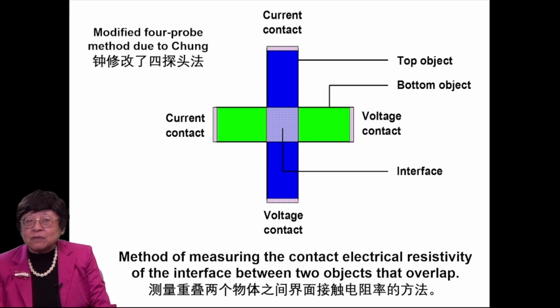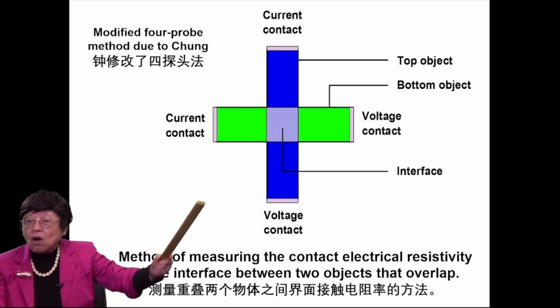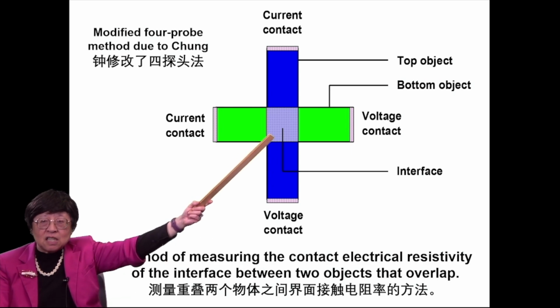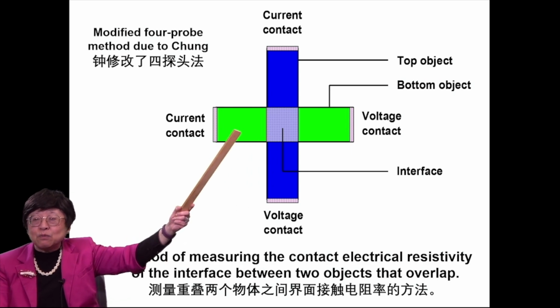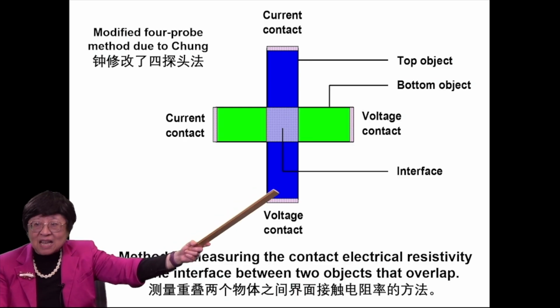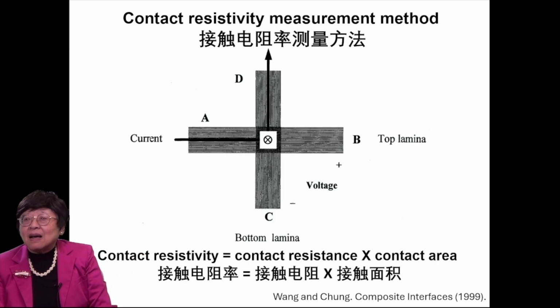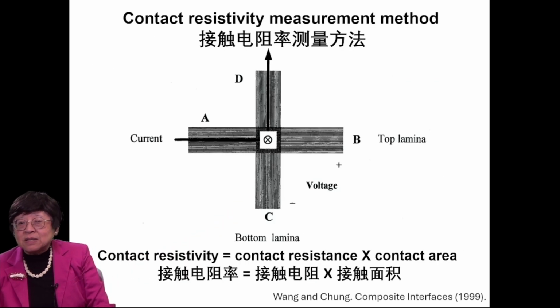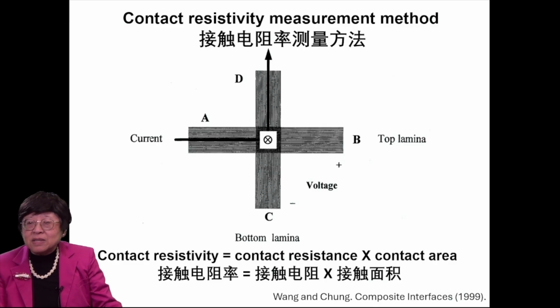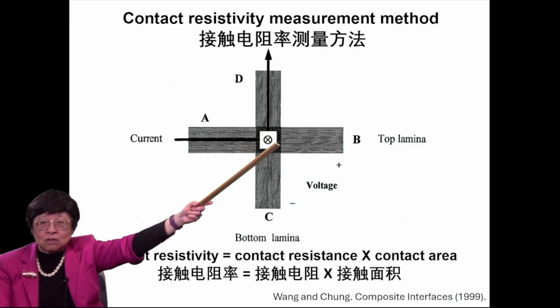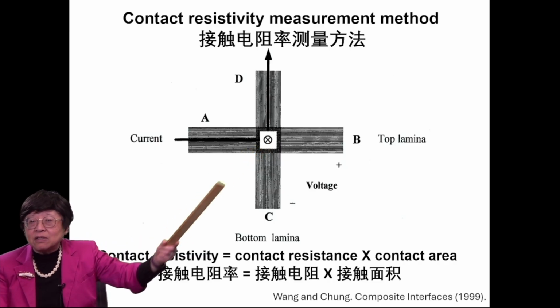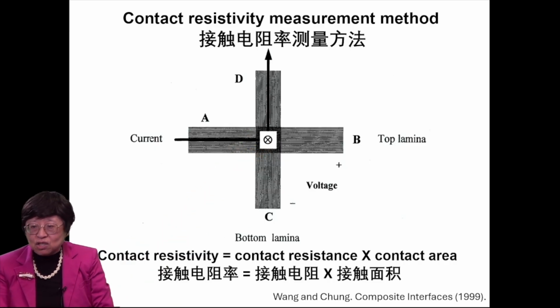And this method works very well, provided that the contact resistance is considerably larger than the volume resistance of the four legs that stick out. The contact resistivity is equal to the contact resistance of this junction times the contact area, that is the area of this junction.